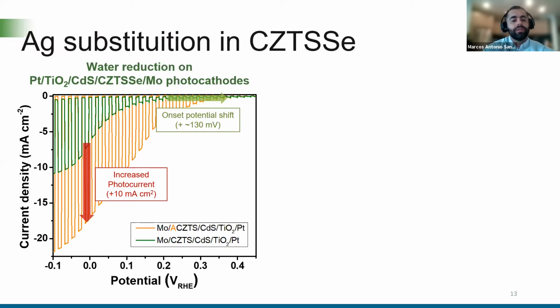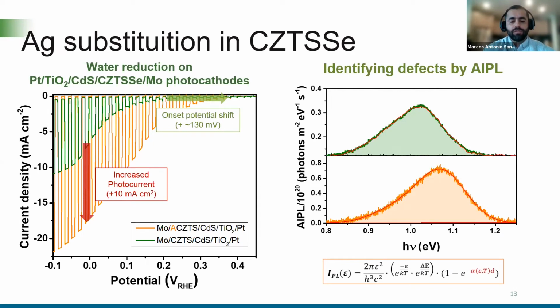In that case, we obtained the photovoltage from the JV curves, and for that we need to fabricate the whole device. Here, rather than that, we calculated the photovoltage of the absorber layers by absolute intensity photoluminescence at different light intensities. We used the black body emission to obtain the absolute intensity, and we fitted these curves with the Katahara modified Planck equation for a PL emission, considering in this case the sub-band gap states, and then we determined the photovoltage.